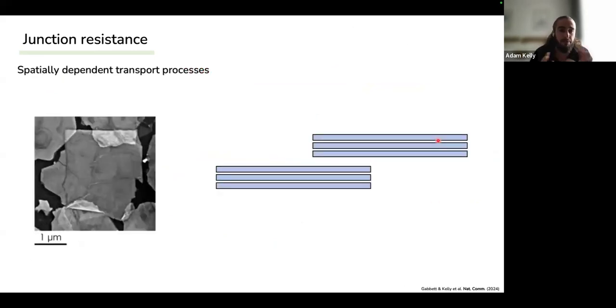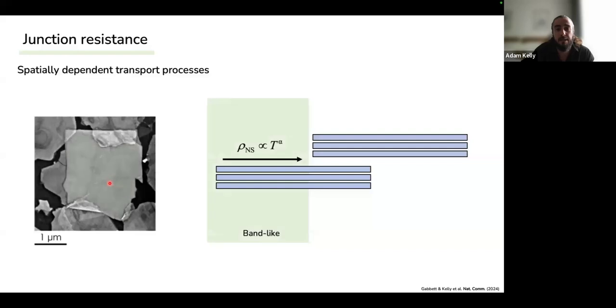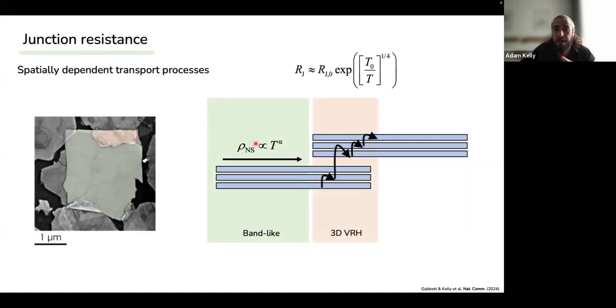So let me visualize this for you. Imagine we have a carrier like an electron moving within our basal plane. This moves at a very efficient band-like transport process. When the carrier reaches the junction up here, it then has to hop between the nanosheets and between the layers, usually through 3D variable range or activated transport, which is less efficient than the band-like transport within the nanosheet. And then as it moves off into the next nanosheet, it moves off again at an efficient band-like process.